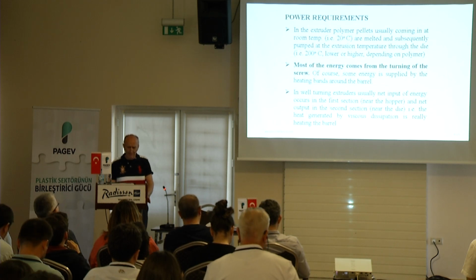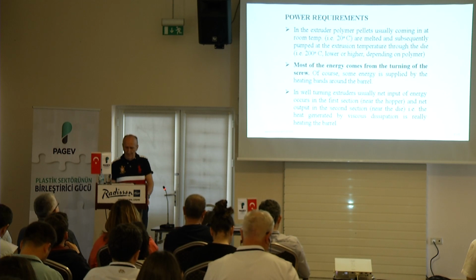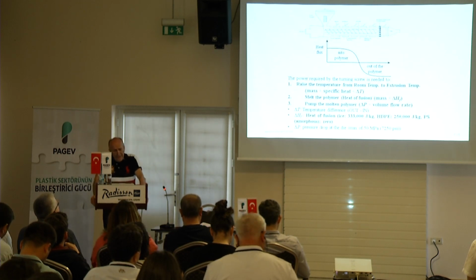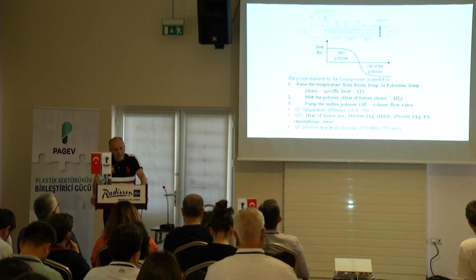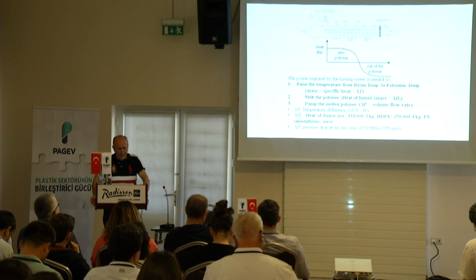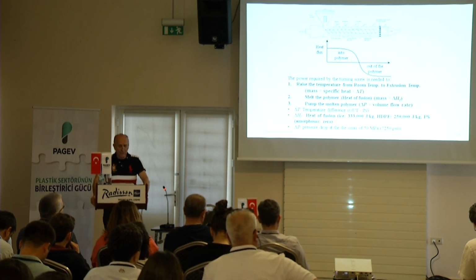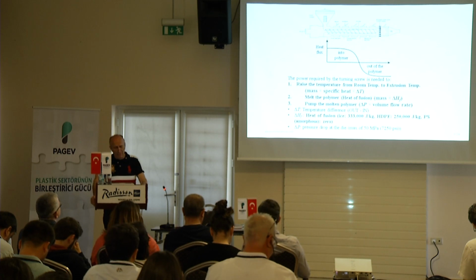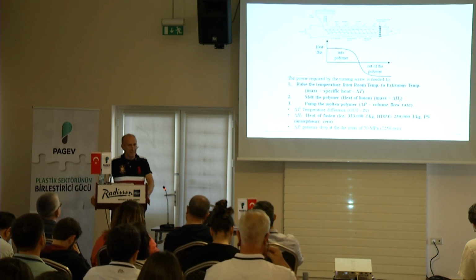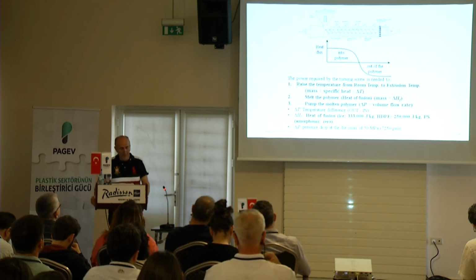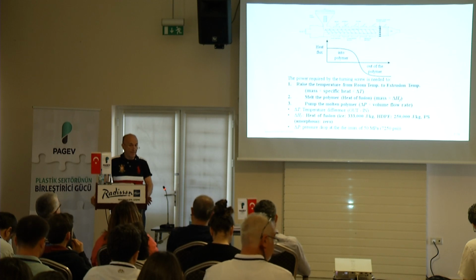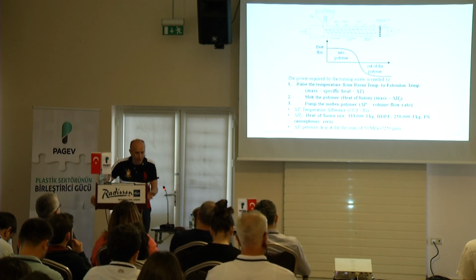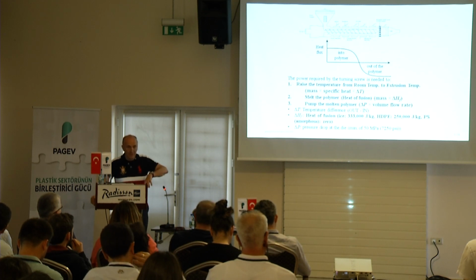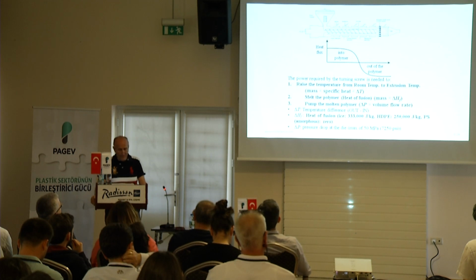Now, for power requirements, the calculations are rather simple. What we want to do is calculate the power that is inputted by the screw by determining the energy required for the polymer to be raised from room temperature to, let us say, the extrusion temperature of 250 degrees, the energy required to melt the polymer, which means the energy we have to supply to overcome the heat of fusion, which is the opposite of heat of crystallization, and the energy required to pump the polymer.